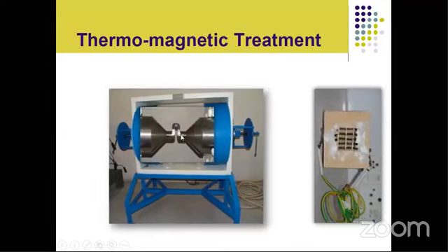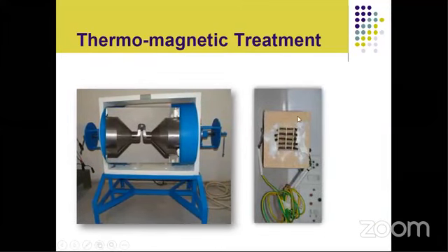And for heat treatment, we made a heater, which we put on this U-shaped magnet, and a temperature of 800 or 850 degrees Celsius is achieved. For a certain period of time, 5 minutes, 10 minutes, or 15 minutes, this magnet is heated at that temperature, which is below the Curie temperature.